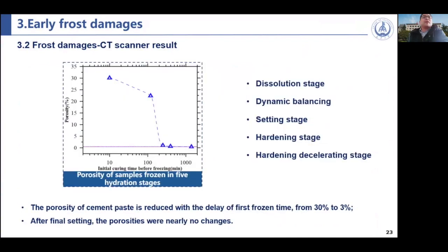This is the porosity of the cement paste measured with the CT scanner. We can see that the porosity of cement paste is reduced with the delay of the first frozen time from 30% to 3%. If the freezing happens after the final setting, the porosities show nearly no changes, especially for the last 2 points.